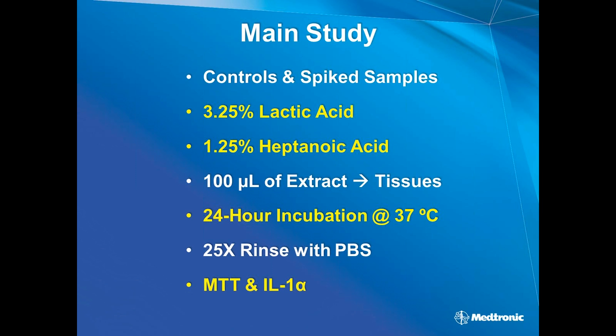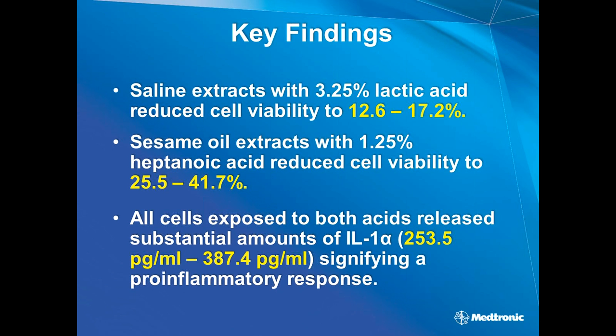We decided that a 24-hour incubation was sufficient at 37 degrees. And when that's over, then they take those little discs that I showed in that cartoon in the L'Oreal picture. They wash those 25 times with this phosphate buffered saline, and then they run the MTT assay and the cytokine assay, which is an ELISA method, actually. So what do we find out from this main study?